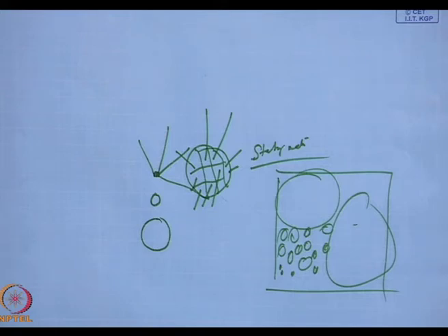Yesterday, I will finish off by saying what I was talking of yesterday. The Ferrari cars, the top of the line F1 cars. Their beauty is the coating thickness has to be within plus minus 1 micron, and the root mean square surface roughness has to be less than 10 nanometers.